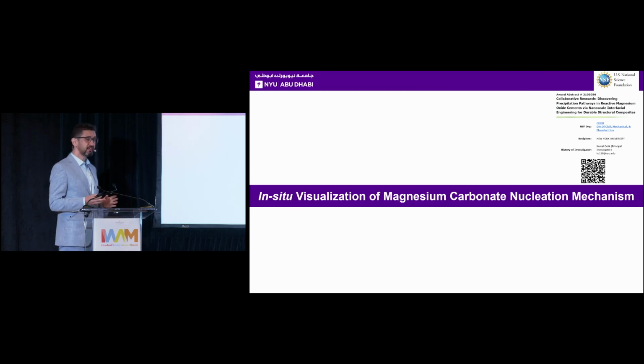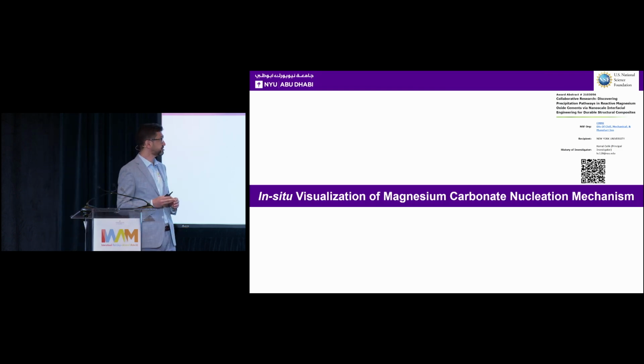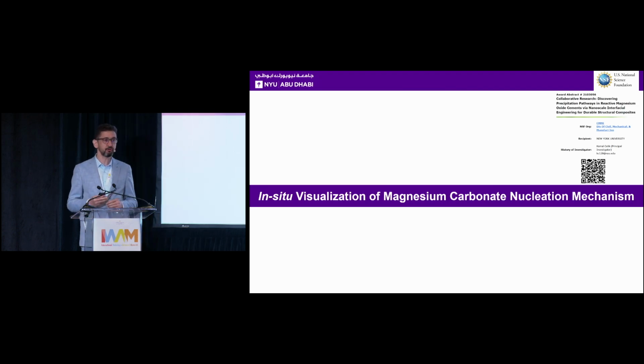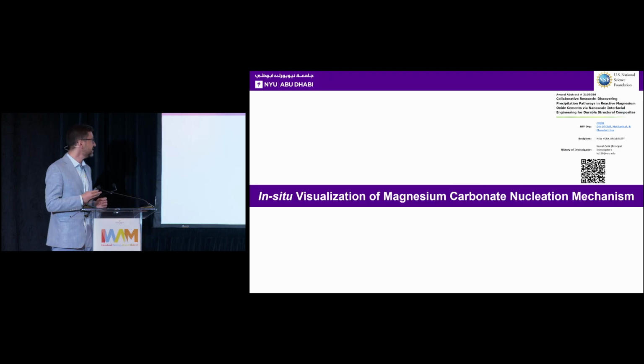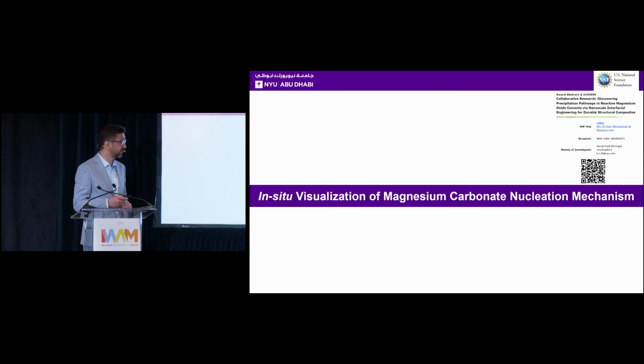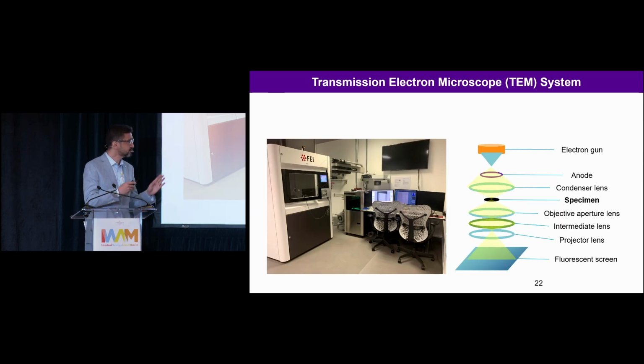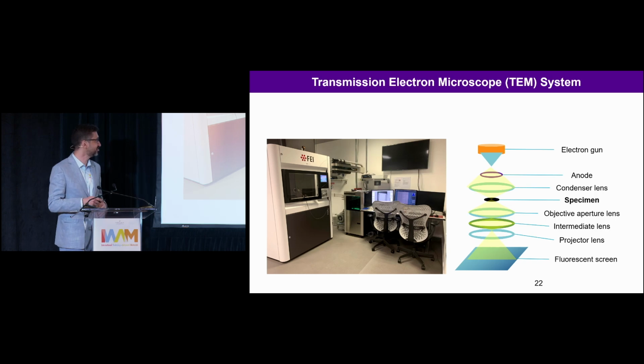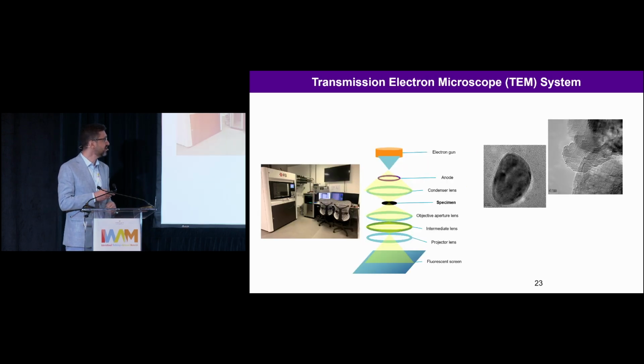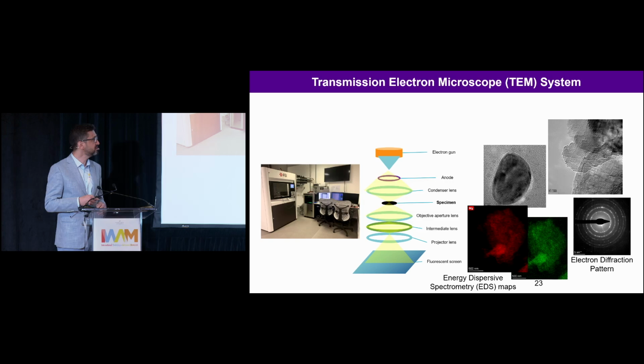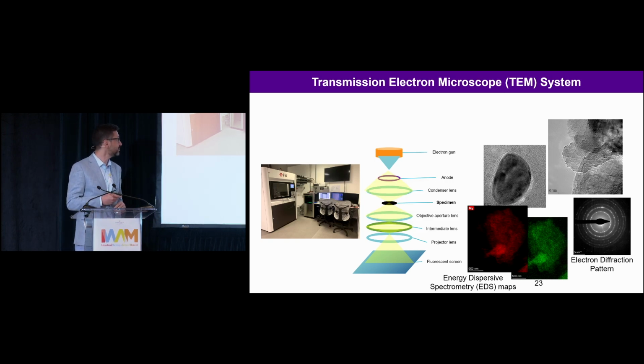And in another project funded by NSF, we want to understand nucleation, growth, and phase transformation mechanisms with in situ visualization of magnesium carbonate nucleation. This is an ongoing project, so these are preliminary slides that I am not going to go into too much detail. We use transmission electron microscopy, similar to light microscopy, but instead we use an electron gun. Then we were able to look into the morphology, diffraction pattern, and chemistry or EDS maps.